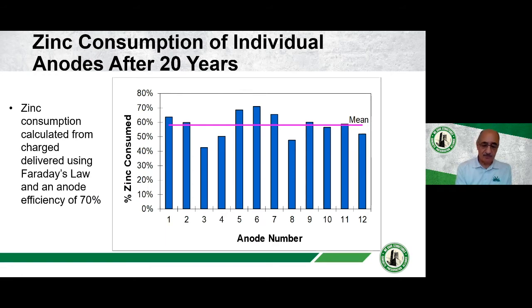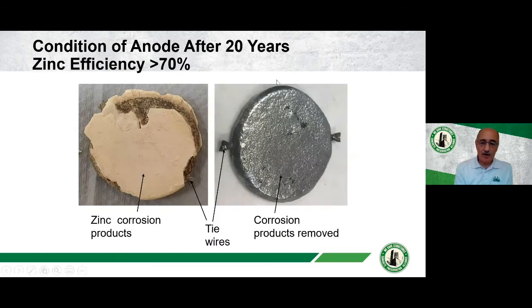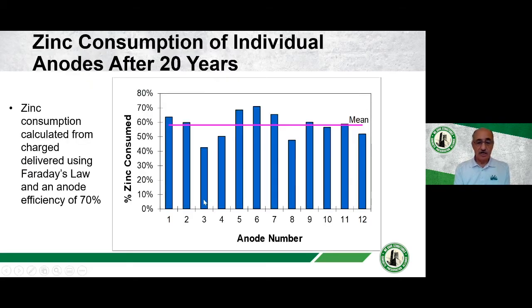What we actually found from that, if I can just go back to that slide again, by taking off the corrosion products and measuring and weighing the anode, we could find an efficiency of how well the anode was actually performing. And the way that we did that was, because we're monitoring the current with time of all individual anodes, we knew what the current delivery was from this particular one. We converted that to charge, and using Faraday's law, we calculated a mass loss, the amount of zinc that we actually lost, and compared that to the actual weight, and that gave us an efficiency which was at least 70%.